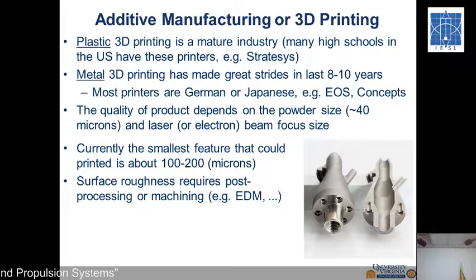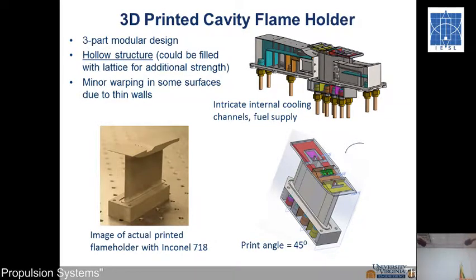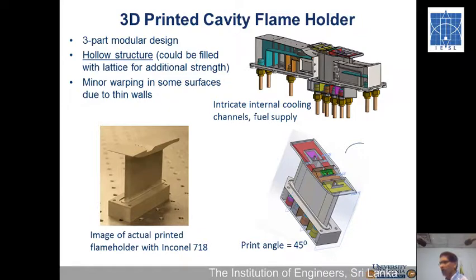Okay, so this is the internal drawing of this part. In fact, we printed it in 3 parts, 3 modular pieces. So this is the base, the support material, which is very simple. They have intensive cooling, but this is the critical part. So we designed this so that we can change this geometry as needed, right? And in this part we have 5 cooling channels coming from the bottom up. So there's one cooling channel here, another in here, and the most critical part is this part here, and then the downstream here. So inside this there are 5 cooling channels, and this is a very thin wall,